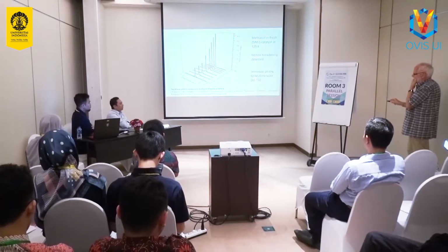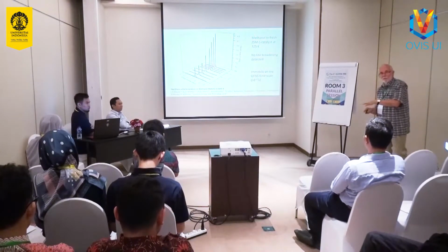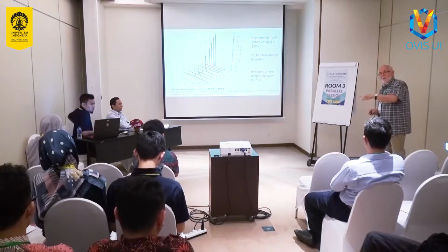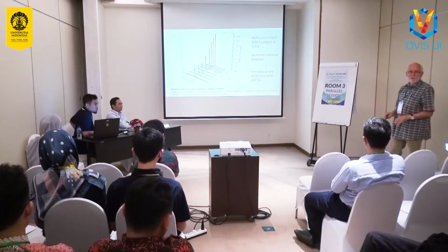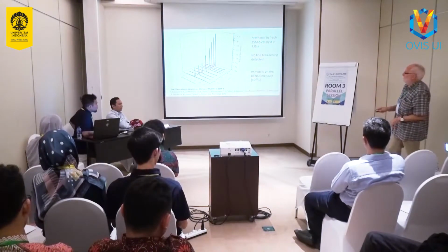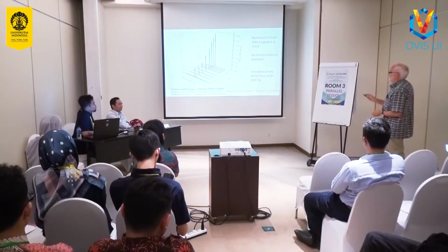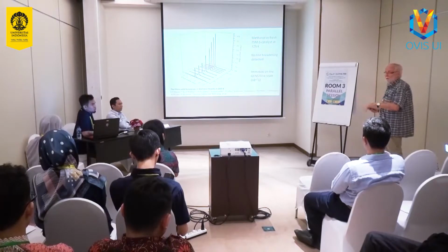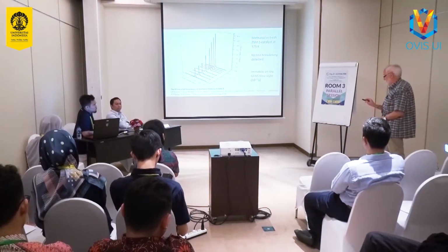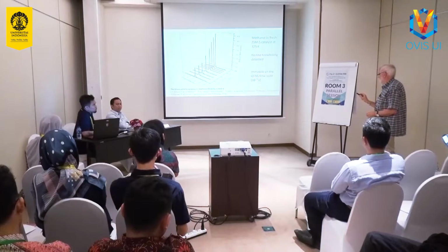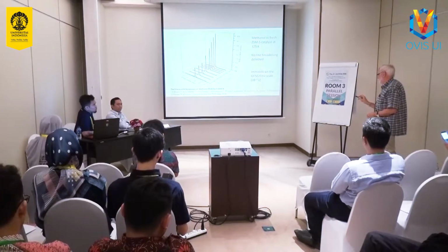That could be because it's dissociated, of course, forming a methoxy group. But it could also be because it's very strongly hydrogen bonded. We can't distinguish that from the QENS experiment. But the methanol in this zeolite is not moving, whereas in hydrogen Y it was. The hydrogen bonding in hydrogen Y is weaker than in ZSM5.